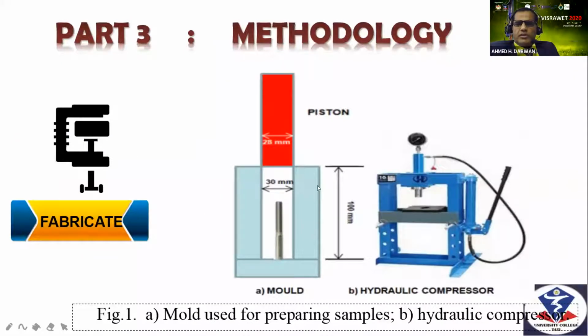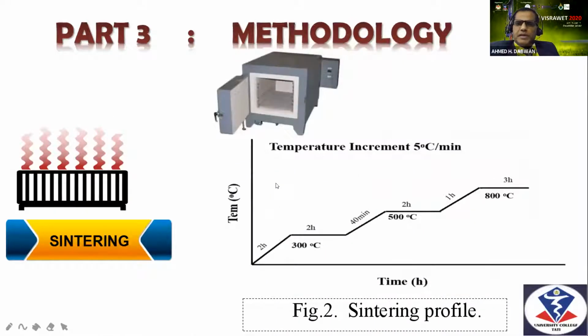We use a hydraulic compressor to make the mold. Inside the mold we put pressure. And then finally after that we make sintering, because this sintering step is very, very important. It will decide your porosity. If you increase the temperature suddenly, it may make cracks. So you have to increase the temperature gradually until you get the suitable porous media. The shapes we got are something like that. We take these samples and we go for analysis.